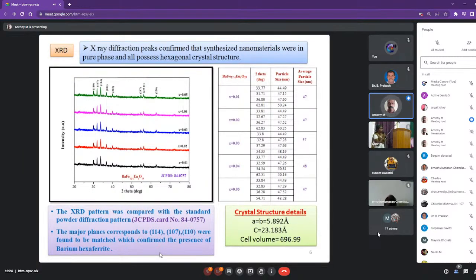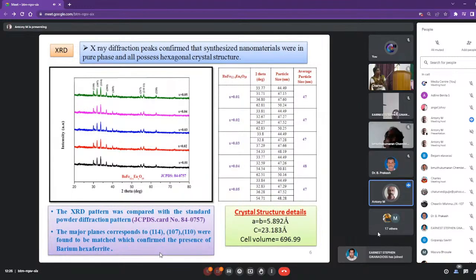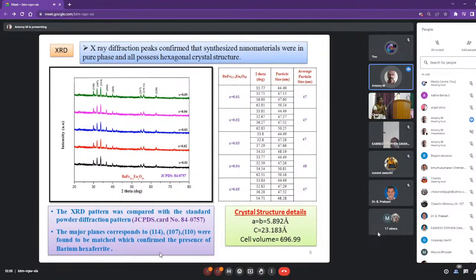This is the XRD pattern for my sample. The XRD confirms that the synthesized sample is single phase, and the XRD pattern was compared with the standard powder diffraction pattern also. The JCPDS card number is 84-0757. The major corresponding planes are 114, 107, 110. The major plane is 114, and the Scherrer equation states the average crystallite size of the sample for various ratios. The average particle size was calculated using a size distribution.